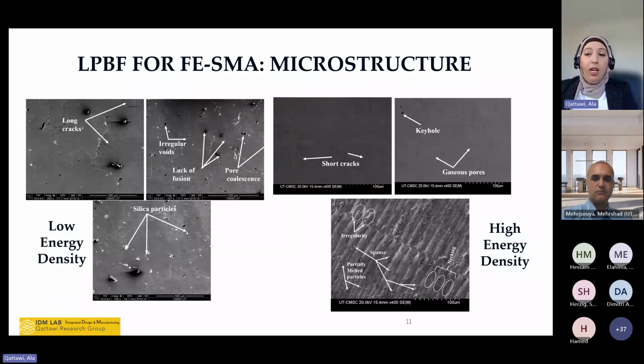And then on the other hand, at high energy density, where we have high laser speed and high laser power, we can also see certain defects. If you are in the additive manufacturing world, you'll understand that though additive manufacturing is a very viable process to produce materials, we are limited in the window where we can get good mechanical properties of any material. So even at high energy density, processing very fast to increase the production rate, we still see a lot of defects. And this was one of the optimizations where we need to be in a good window for the iron shape memory alloy, and at the same time reduce these defects on the micro scale.